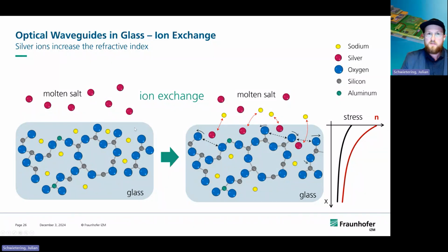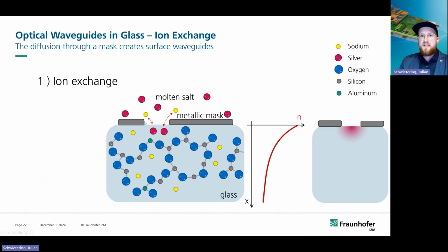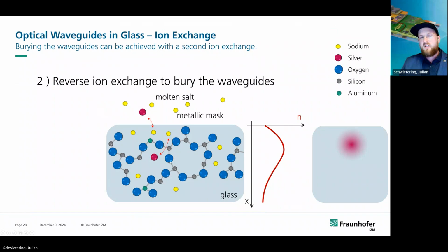And this is the way we are doing our waveguides. So if you take a metallic mask and you make this ion exchange just there where you want to have the waveguides, you can locally increase the refractive index. And in a reverse ion exchange, you can take the silver ions that are directly on the surface of the glass, and you can exchange them with sodium. And afterwards, you have a buried waveguide.